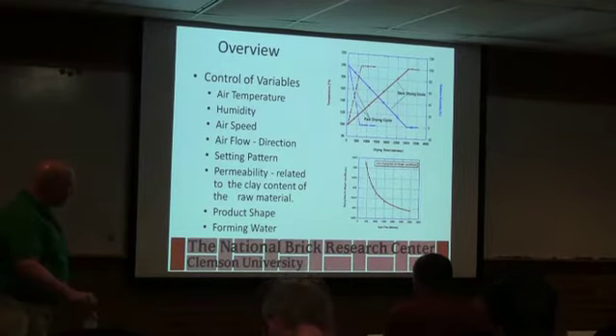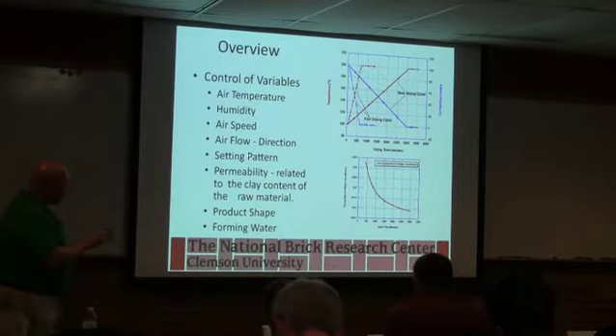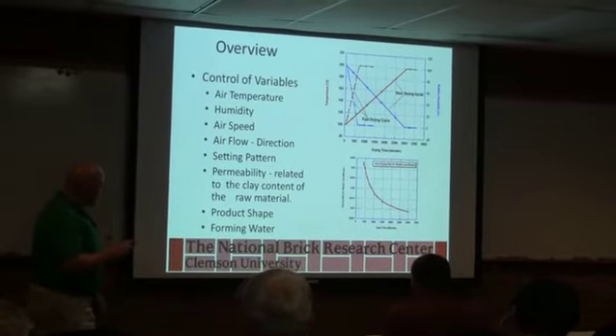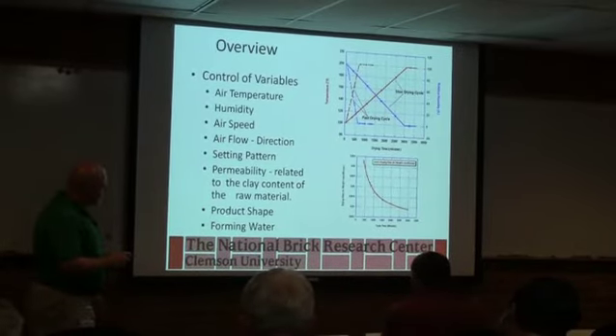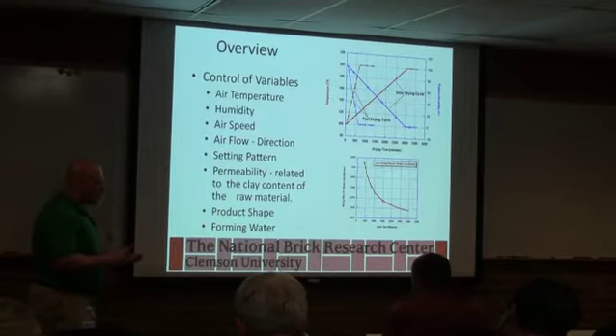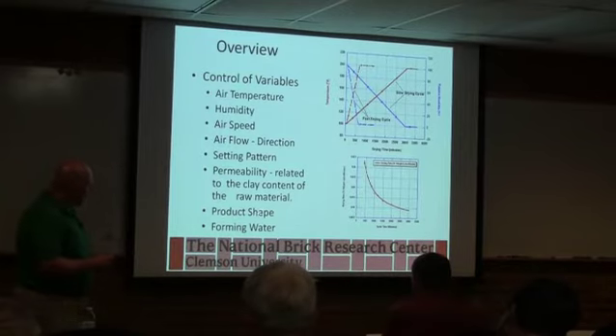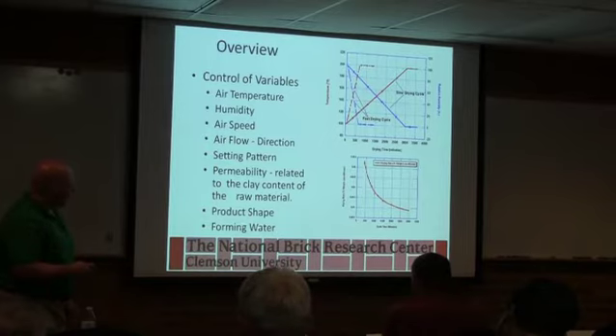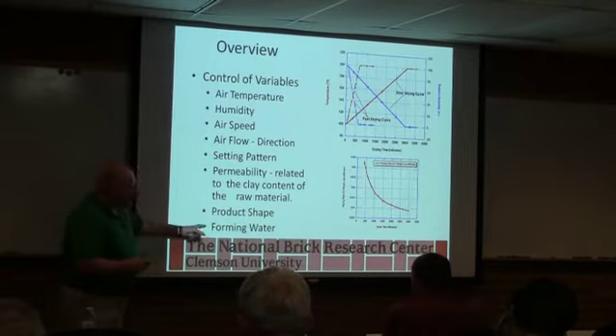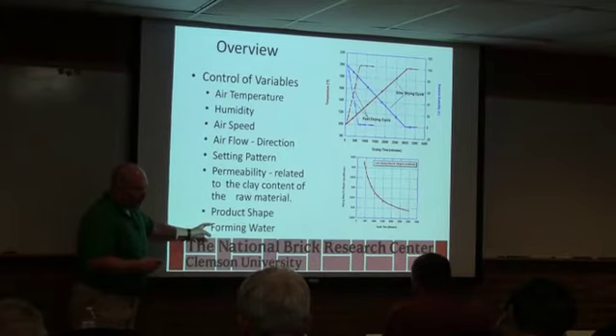And they can get faster rates out of that. How open is the setting pattern? How accessible is the brick to the air? The permeability of the raw material, the shape. How do you design the coring? Because coring does come into play when controlling drying, and keeping the forming water to a minimum. Okay? The more water you put in, the more water you've got to take out, and the more water you put in, the more shrinkage you see.